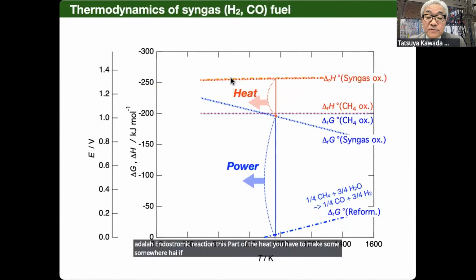For example, if you use methane as the fuel, it must be first reformed. And the reforming reaction is an endothermic reaction, so you need heat. This heat you have to make from somewhere. But if you use this product gas in a fuel cell, you will have heat. Then this heat can compensate the reforming heat. So only this size of exhaust heat remains. And of course, you have some overpotential, so the heat of this part will be emitted. But the ideal efficiency of methane fuel can be counted as 100%.